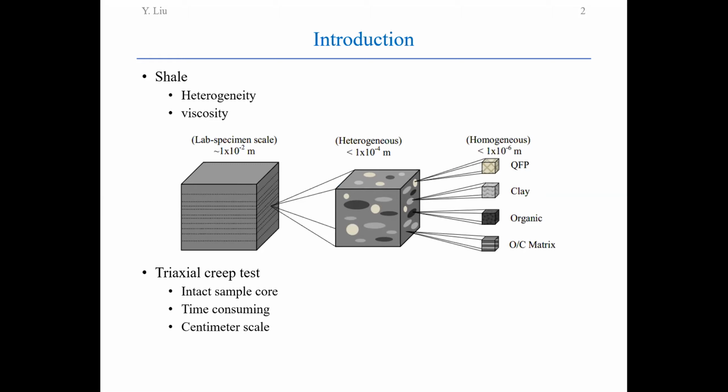Second, triaxial creep tests are time-consuming. They typically last for days, if not months. Third, triaxial creep tests are designed to measure the creep properties of the shale mixture at the centimeter scale. It is not possible to study the mechanical processes at the mineral component scale.